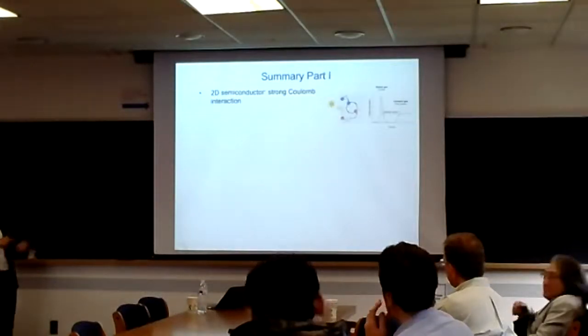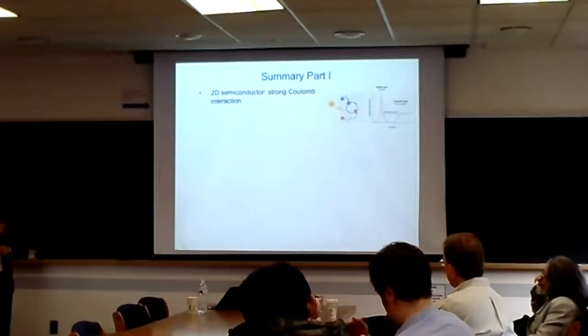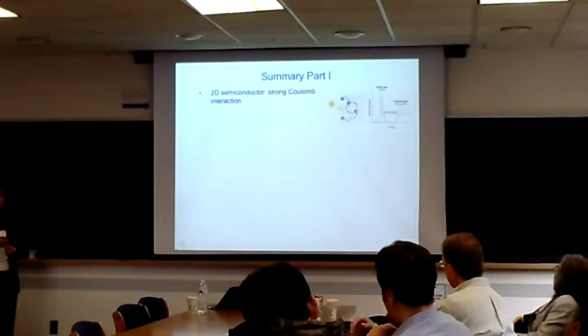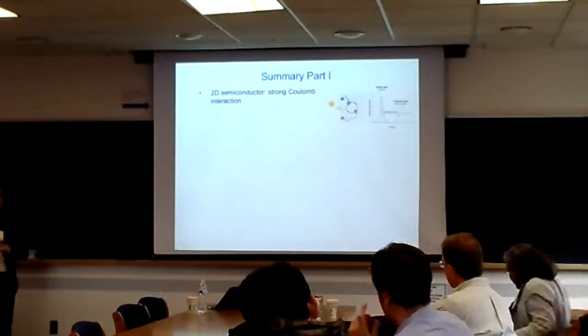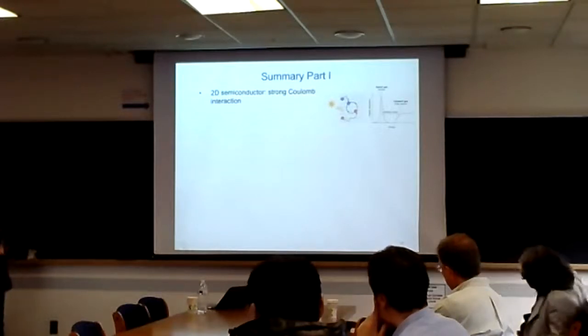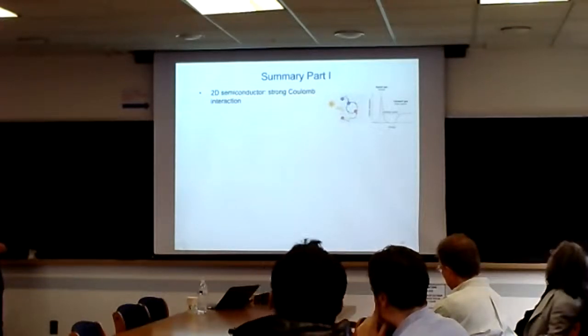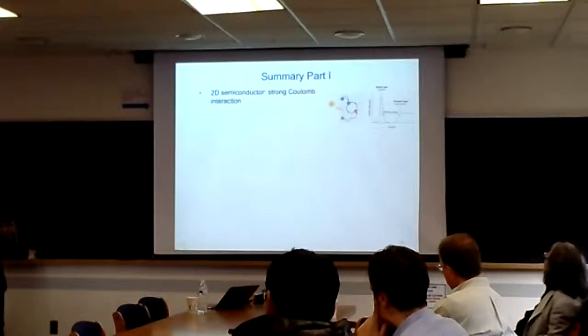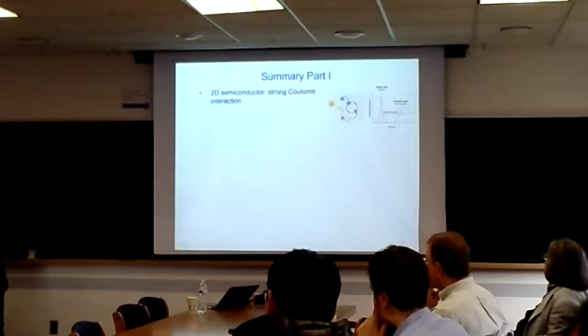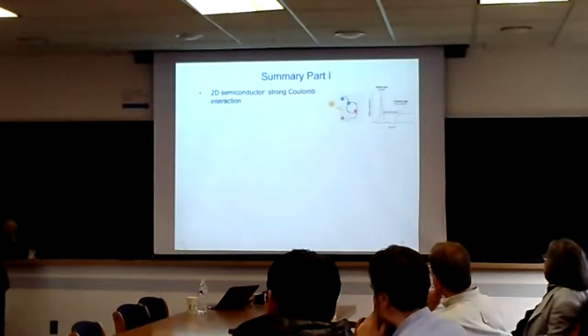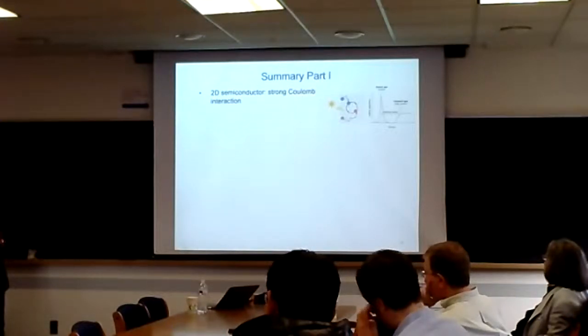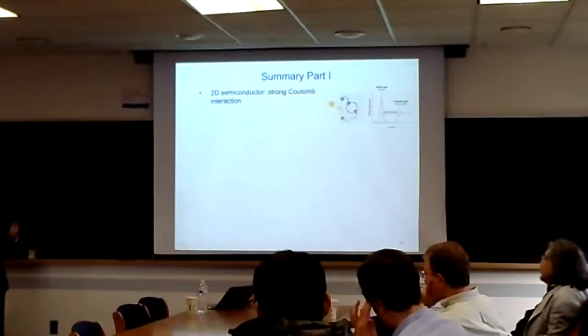So to summarize, is charging of the sample an issue? I mean, of course, you change the dielectric environment, so the photoelectrons will also experience that. Yeah, so it's insulating, right, BN underneath. Exactly. So this is a bit of a mystery. We have this whole thing sitting on top of a monolayer of graphene, and it really works well that there is no charging. So when you hit it with 145 eV, the optimized X-ray energy for best matrix elements, you see that from the graphene you can replenish through the BN.